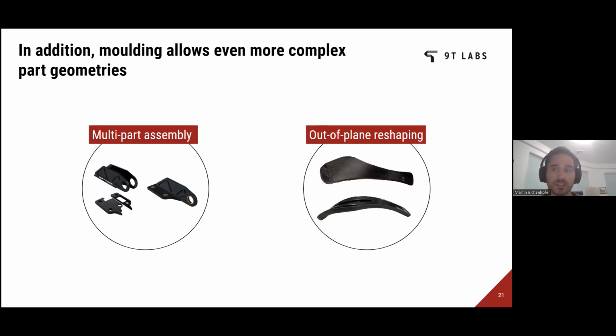But the other aspect is also that the molding enables us to make new things, have an enlarged design latitude. Or we can just do new designs, designs we could not do before. So one is that we bring in software, we split an application apart into sub pieces, which are optimized, and then they come together in the molding, and then they're co-welded or co-consolidated together. And this enables us to do applications like this hinge, which we show a lot, which you cannot do with conventional means, because you have fibers that penetrate from the vertical plate into the bottom plate.